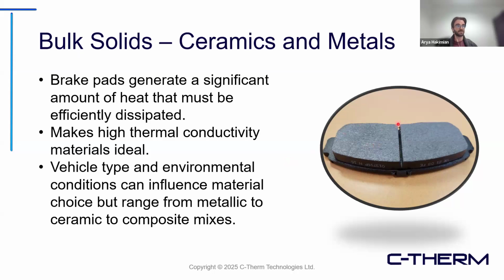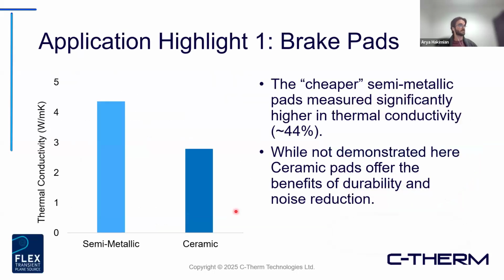But as an example of measuring something like this, again a bulk material, this is essentially just an off-the-shelf brake pad that was purchased. It fits the sample size requirements for the 13mm TPS, and we can do some testing here. We looked, quite simply, at a semi-metallic versus ceramic option. From a thermal conductivity perspective alone, we're noticing quite a difference between those two materials for the brake pad application. Again, there are a lot of other factors that go into performance for something like a brake pad, but just from a thermal perspective, and looking to characterize the thermal conductivity of those different sample types, TPS and the TCkit would be a great option to enter into that type of investigation.